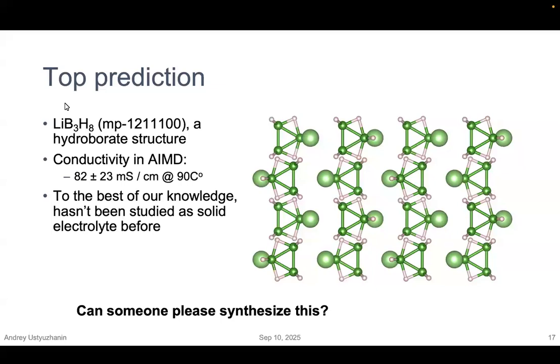We contacted the team in Switzerland, and they work with hydroborates quite extensively. But they said, okay, we need maybe to submit a grant proposal, one year of studies. So their concern is that this material might be not very thermodynamically stable. So it is stable dynamically, so it has a minimum in its configuration, but thermodynamically it is not.